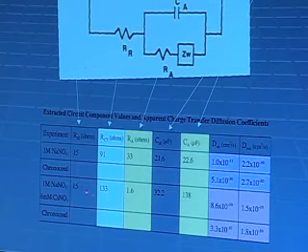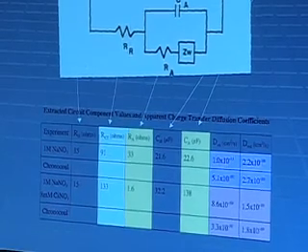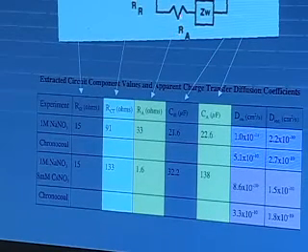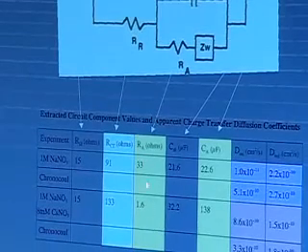This is not pure cesium. You'll notice this is 8 millimolar cesium ions in the presence of 1 molar sodium. Remember, we have to do that because the selectivity of the surface is very high for the cesium ions. But a little bit of cesium does a little bit of damage there on the charge transfer rate constant. So that seems to fit physically well. And now we have this resistance associated with the ions moving in and out of the surface layer, and we would of course want that to change if we have some physical significance between sodium and cesium. And in fact, you see that it is changing significantly, from 33 to 1.6, as we do that.